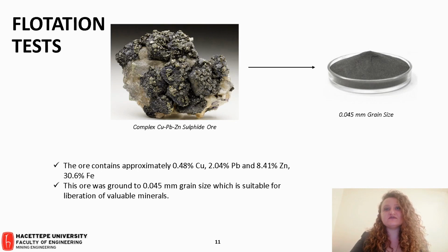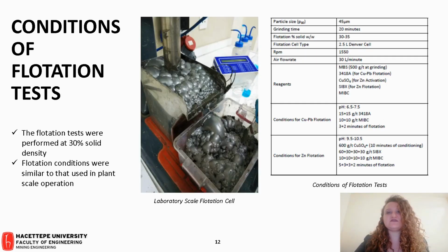Using different ionic concentrations of water samples obtained from ion exchange column tests, flotation tests were performed on a complex copper lead zinc sulfide ore of an Iberian mineral processing plant located in Portugal with a laboratory scale flotation cell. Copper lead bulk flotation was followed by zinc flotation. The tests were conducted firstly with only the synthetic processed water itself, then the treated water samples were used together with tap water by mixing in a ratio of 70 to 30 in other tests.